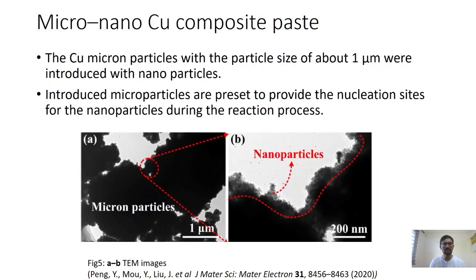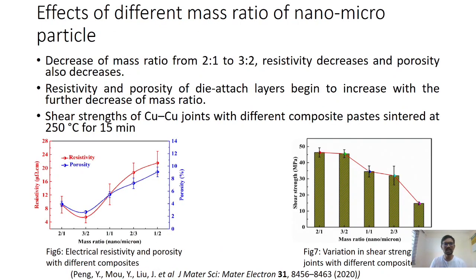In this we have taken 5 ratios of nanoparticles and microparticles, and have studied shear strength and porosity and resistivity. As you know, as the resistivity of the bond decreases, the resistance decreases, and we get good electrical conductivity. And when the porosity between the bonds decreases, we get better thermal conductivity and better heat dissipation.